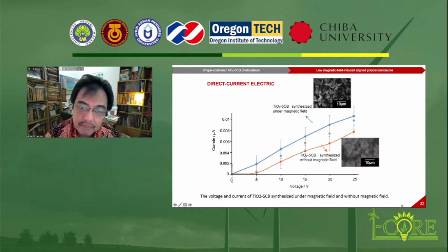This is the relationship between the well-aligned structure and the direct current electricity. It can be seen clearly that the voltage and current of the titanium dioxide 5CB synthesized under magnetic field produce a higher slope than without the magnetic field.